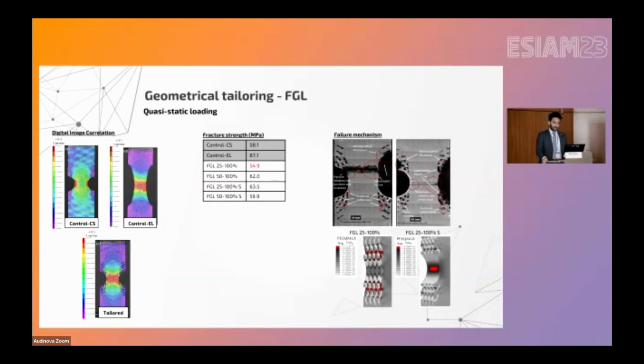The specimens that didn't have that shell had the failure all the time within the lattice part. And obviously, this was shown in our elastic-plastic analysis, which showed the highest plastic deformation within the lattice part. For the specimen with the protective shell, we could see that the main point of criticality remains on the notch bisector line.